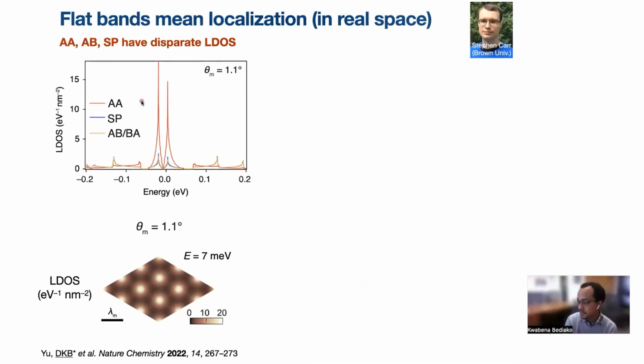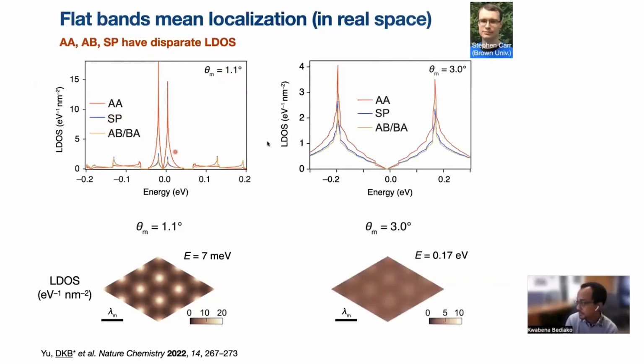If we look at a twisted bilayer graphene of 1.1 degrees, you see that the density of states enhancements that you could measure for the whole system are mostly, or overwhelmingly, localized on these AA sites of the graphene, and much less so on the rest of the graphene structure. Whereas at 3 degrees, you have more smearing out of the electron wave function, and very little discrimination between the different stacking types.